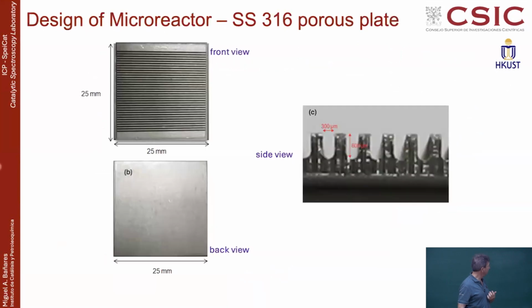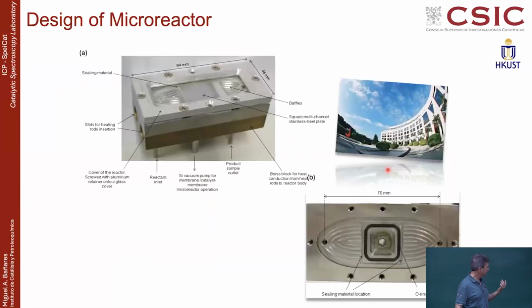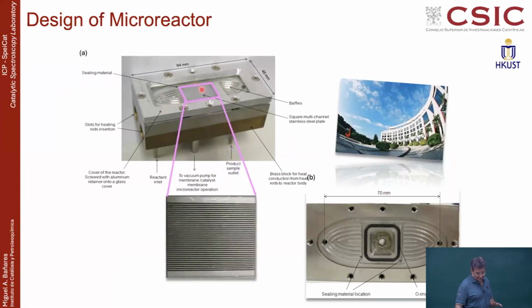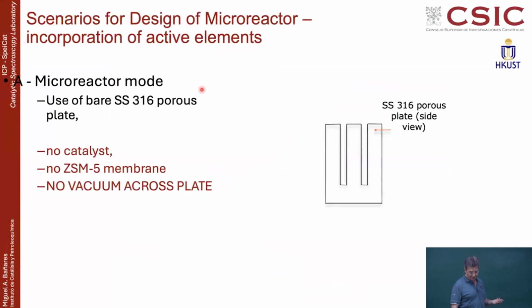And so what we did is that we have a lot of grooves, these kind of little grooves over the reactor. You see it's just 1 inch by 1 inch on one side, and on the back side basically is this porous material. From the side it looks like this. You have a lot of channels. And why do we do that? Remember that this is a highly porous metal, stainless steel. And then what we do is to put on top of it the liquid feed so that it will go through these channels and they will react. And what do we put in these channels? Well, a catalyst. And so the channel is like that. Remember, this is always a porous stainless steel.